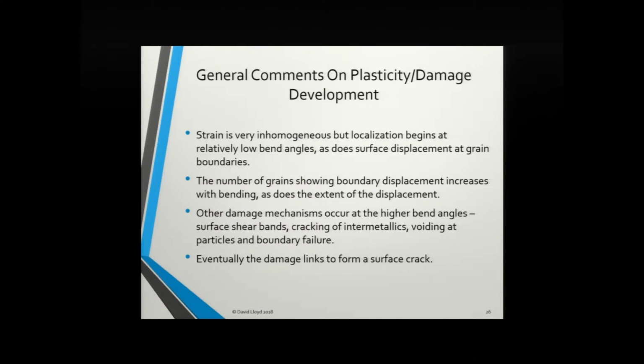You'll get localization in significant shear bands. That's a function of the alloy and a bunch of things. Cracking of intermetallics, voiding, and the usual fracture processes that we're all familiar with. And eventually it all links up, and that's that. Okay, so we've now looked at the mechanics, so we now know what sort of strains we are looking at, where those strains are, and we can relate that back to the microstructure of the alloy.